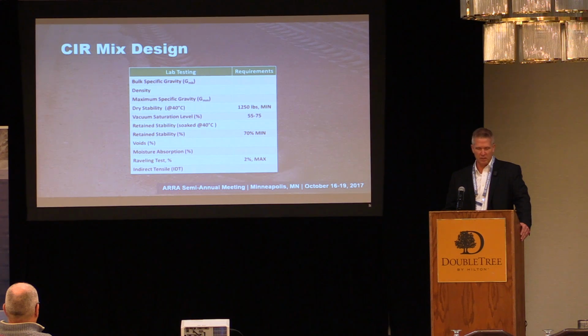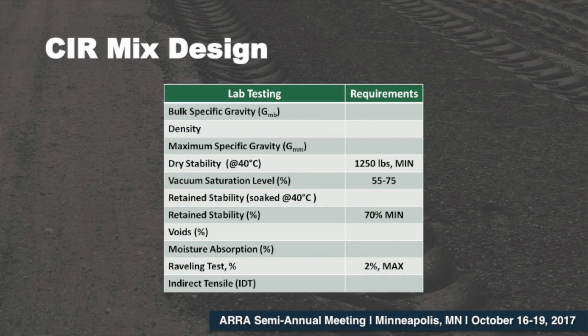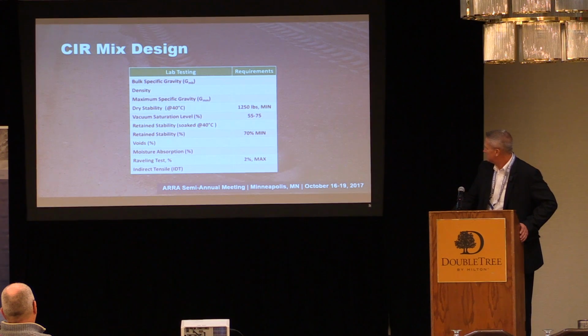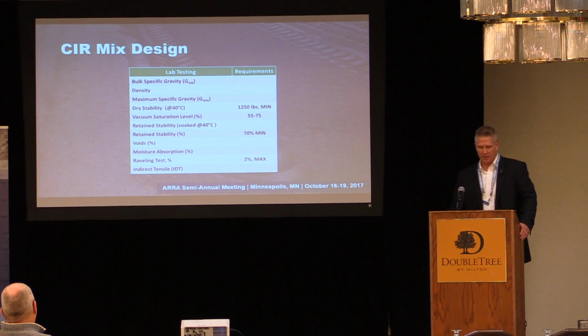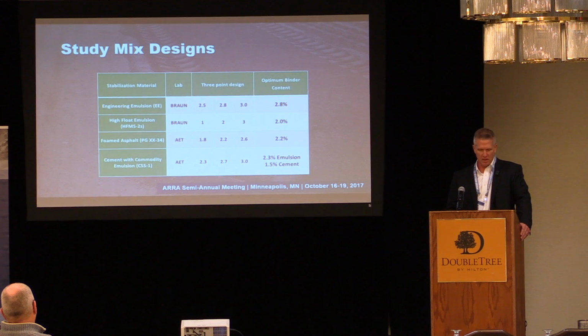And this is just a quick look at the mix design criteria, and you can see that not all the standard criteria that was developed as the original guide spec out of Koch Materials is there. The indirect tensile test was not part of it, but you can see that the raveling test and the retained stability and the dry stability is a key component.